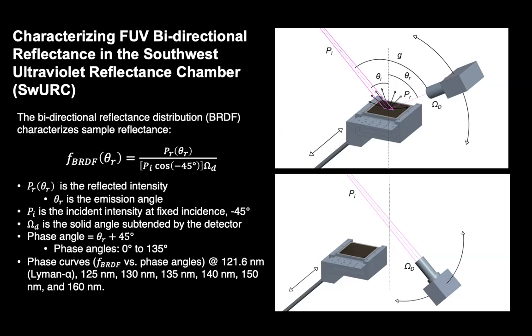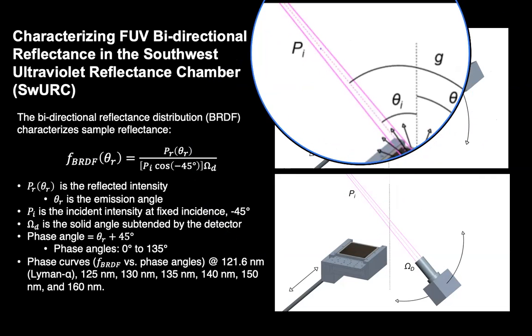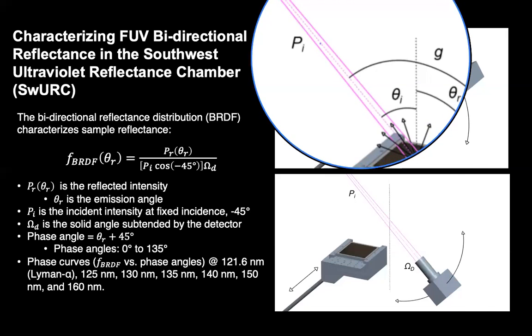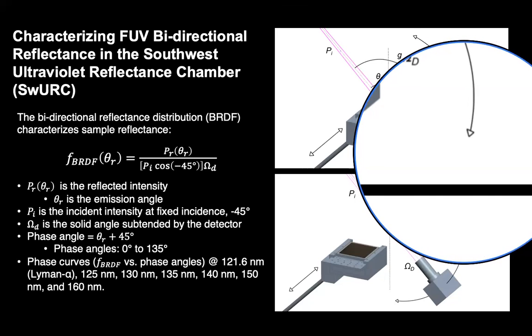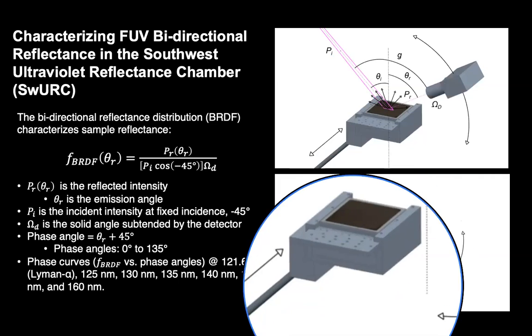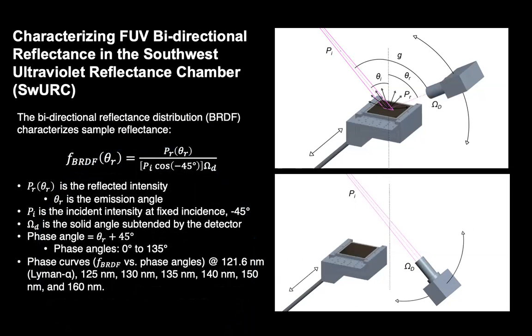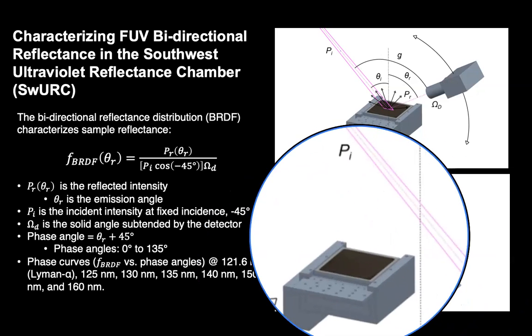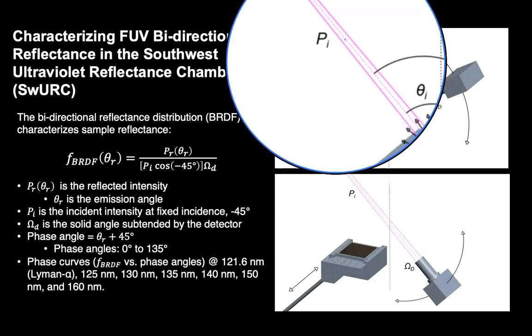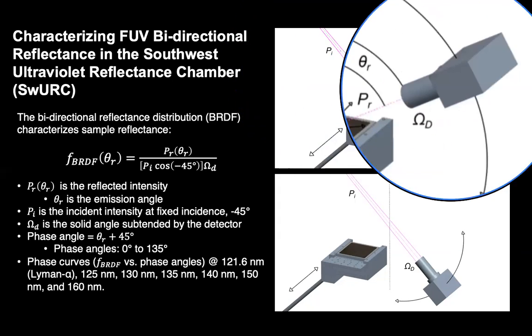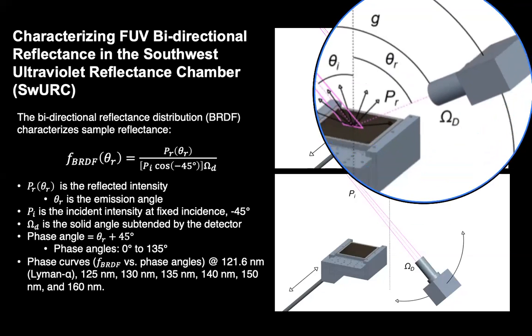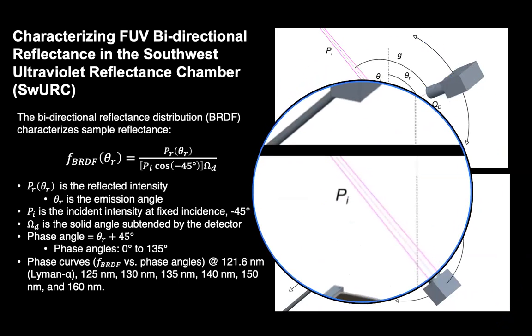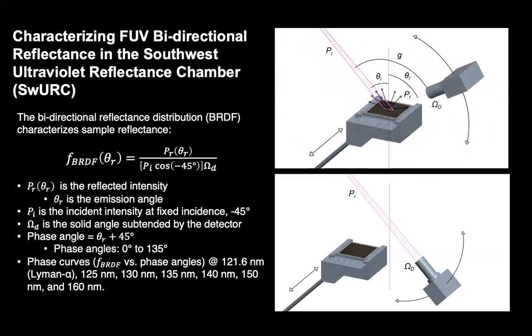In this particular study, phase angles between 0 degrees, in other words, just right in line with the light, to 135 degrees, so basically right in the line path with the sample tray reflected, are available to us. And this is what makes this experiment special. We can actually do absolute ultraviolet reflectance measurements here. Previous studies were not able to retract that sample tray away. The sample tray was just kept in the same spot, and they made a guess as to what the incident intensity was they were using, and then did their measurements based off of that. Here we actually get an immediate measurement of the intensity of the incident radiation, and then we do the reflectance measurements. So we actually get, again, absolute bidirectional reflectance measurements.